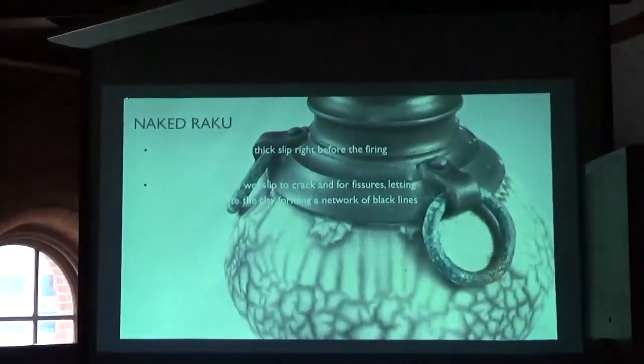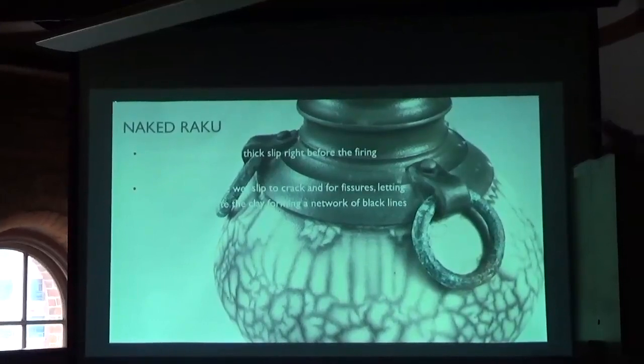like that, that has the black non-treated top part and then all the black network of lines, I can throw that back in the kiln at about 1800 degrees and all of that burns right back up.